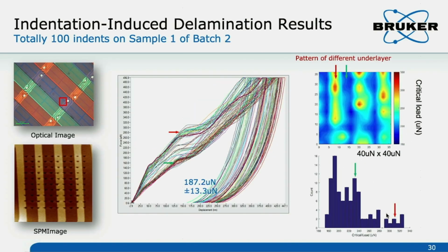So if we look at this, this is the display application. There is a transparent coating, so you cannot see it, but you can see it from the SPM image, because there is still some pattern underneath here. If we just use the high-speed indentation, we can see there are two groups and also the interface. Two groups, critical load, and we can see the critical load mapping. Does that make sense? Yeah, it should make sense because different materials have different adhesion properties. So this is just a very interesting application.